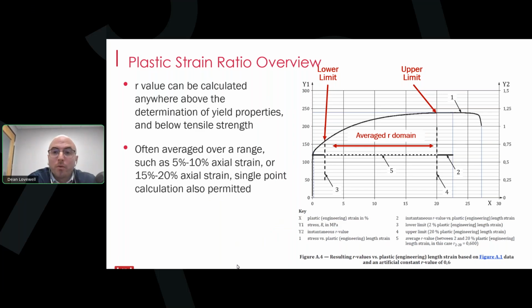The reason why we don't calculate R value from the portion of this curve after tensile strength is because the formula for R value assumes that the width strain is relatively homogeneous throughout the reduced section. After necking occurs, width strain is localized to the position of the neck, so the formulas we use don't apply.